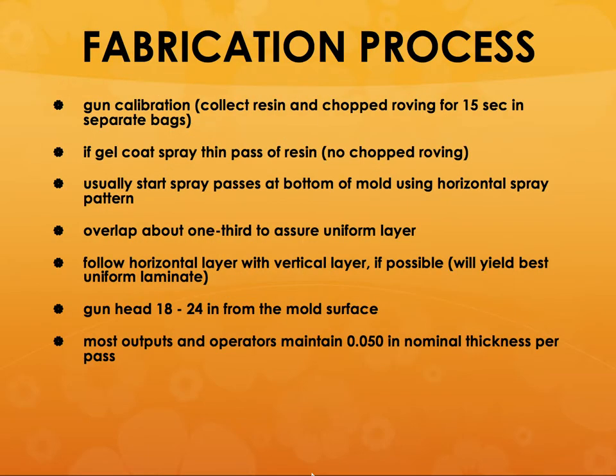So what is the fabrication process? You have to calibrate the spray gun and make sure you have a specific weight, because these are components where the wall thicknesses and the weight of the component have to be accurate, otherwise your quality control is not going to be that good. That means you are spraying a specific volume within a specific time, and everything is automated and controlled. Typically the gun head is about 1.5 to 2 feet from the mold surface, and most operators will maintain about 0.05 inches in nominal thickness per pass.